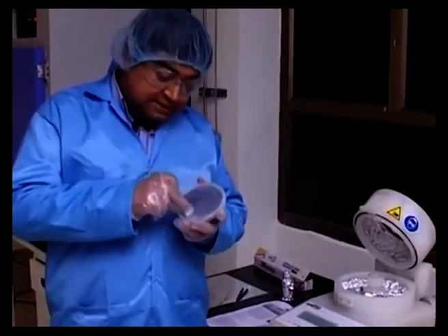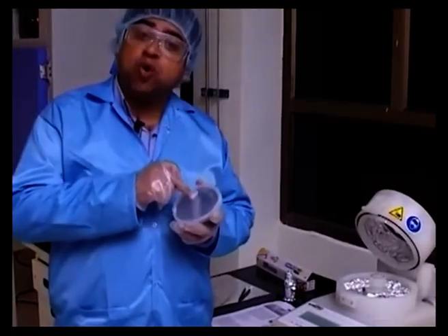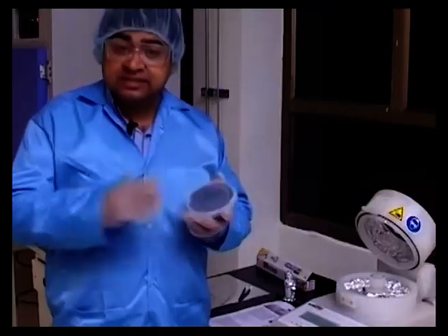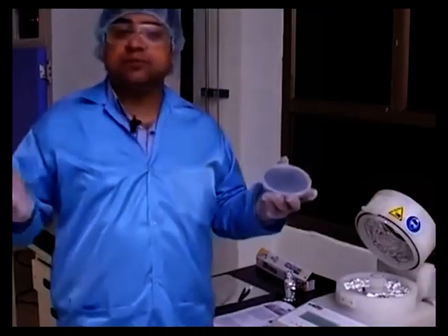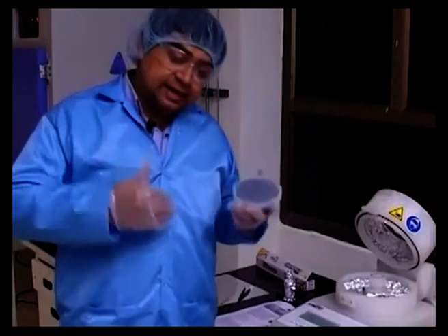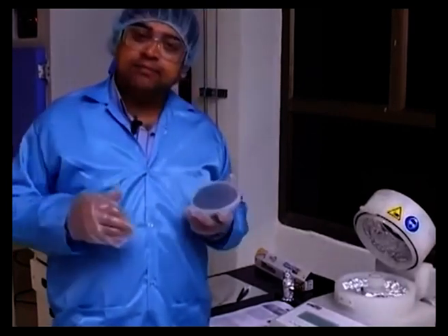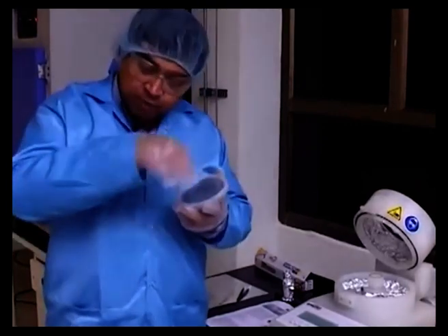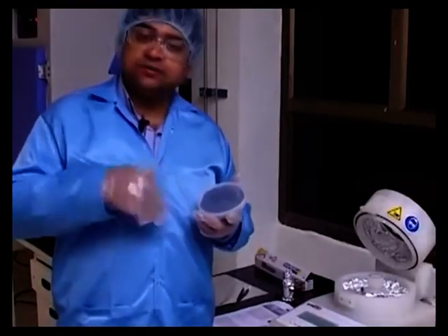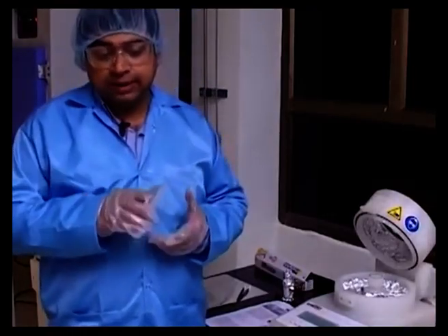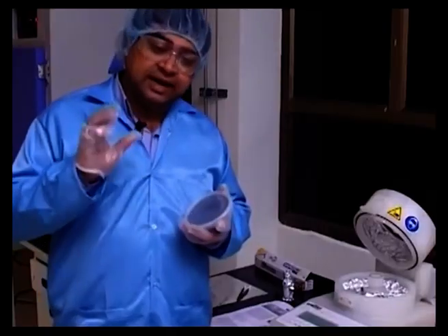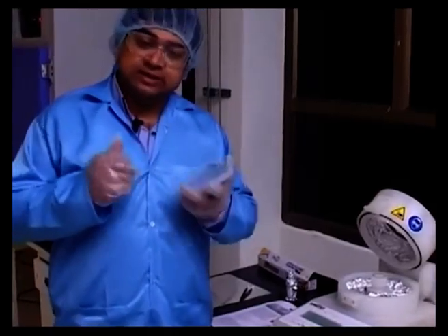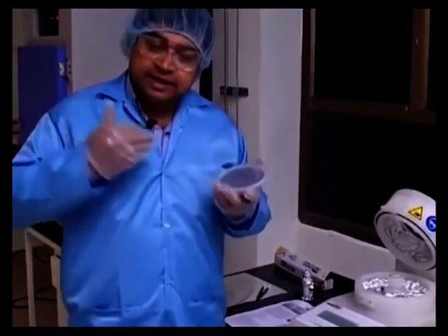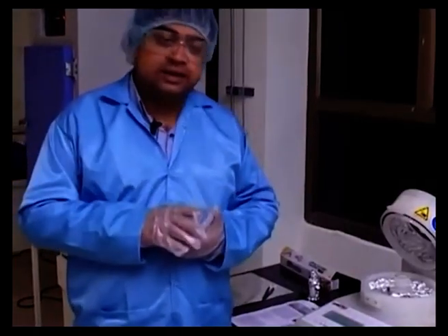So you have to ascertain how much area you need to initially pour or cover so that you have enough resist, since the spinning process is nothing but centrifugation. There is a slow coverage of the surface by the resist which has been poured somewhere in the center, driven by centrifugal forces. The whole idea is that you give adequate resist so that when it goes radially in all directions, it has uniform coverage on the surface.